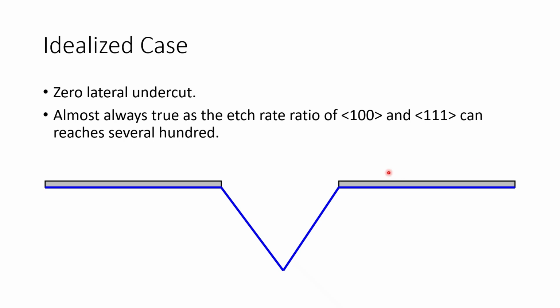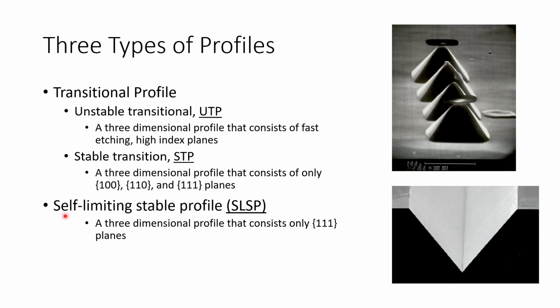The idealized case, of course, is when the etch rate in 111 is exactly 0 or is completely negligible. Then you have 0 undercut. The etch rate is 0 at 111, and the cavity would be bound after forming the inverted pyramid. It will no longer grow any further. That structure is what we call a self-limiting stable profile, SLSP. It's limiting by itself and it's stable. It doesn't matter how long you etch it. Ideally, this is good because in processing you can do over etching and it's not sensitive.